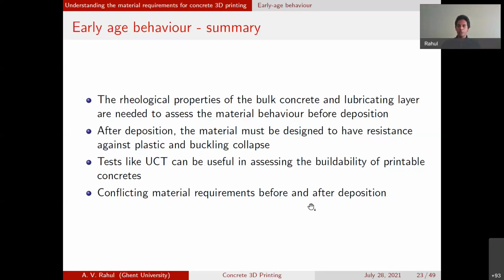One more thing that we need to point out is the conflicting requirement before and after deposition. For the before-deposition requirement, the material should be as flowable as you can make it. The more flowable the material is, the easier it is to pump the concrete. But once it's deposited, the yield stress should be as high as possible so that you can print